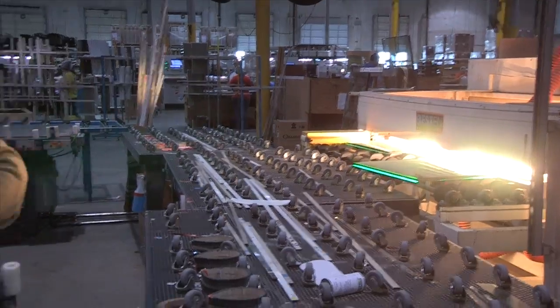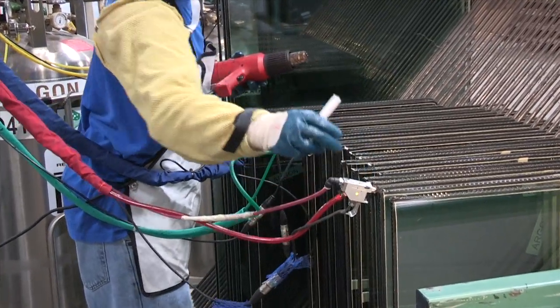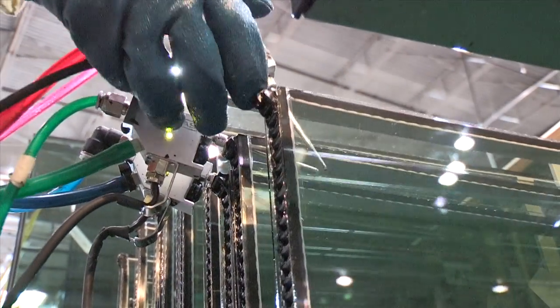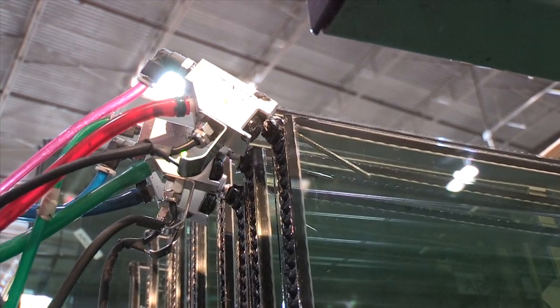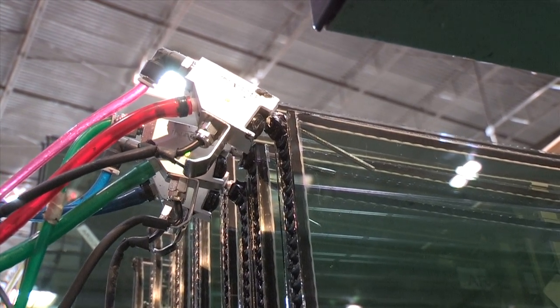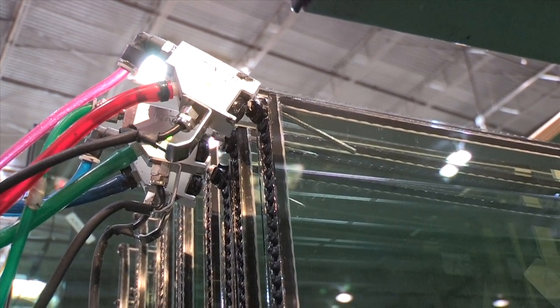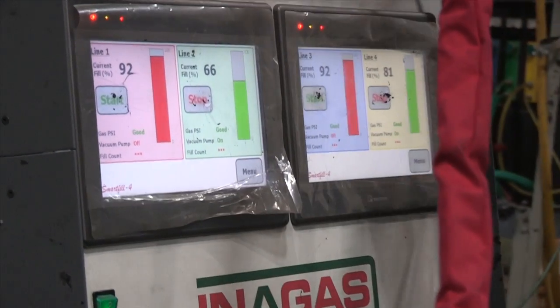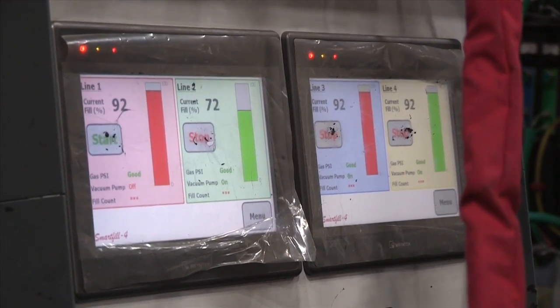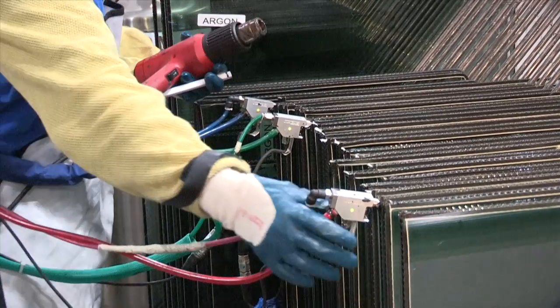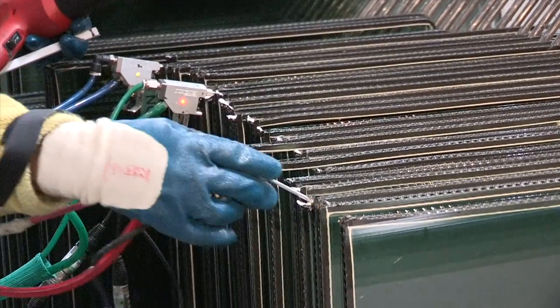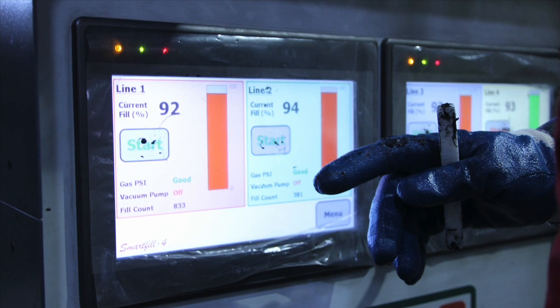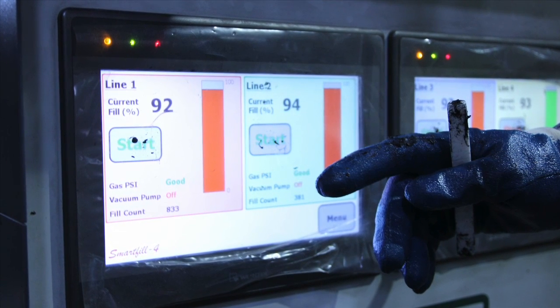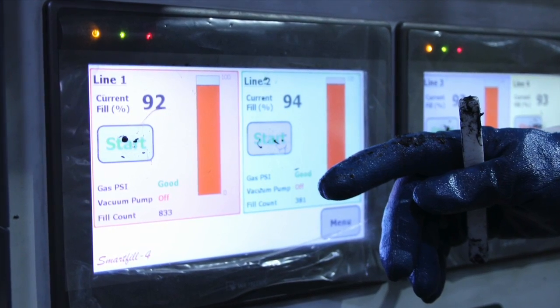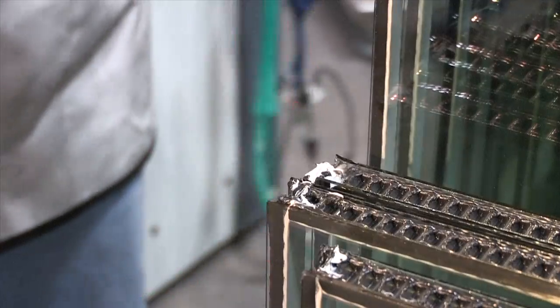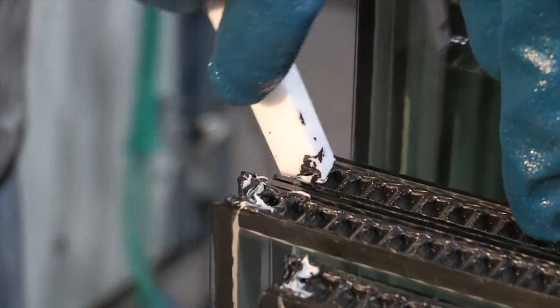After the glass exits the press, argon gas is pumped through a small hole created in the top of the spacer. A needle valve is inserted at the top of the pane, and the gas flow is carefully monitored. The speed of the gas flow is critical. Using a computer-guided pumping station, which measures the gas content, the argon is pumped in and the air is pumped out. Argon is heavier than air. Natural flow pushes the air out. This improves the overall U value by as much as 13%. Argon fill percentage is independently tested periodically. After sealing the hole, the unit is now ready to be combined with the vinyl frame.